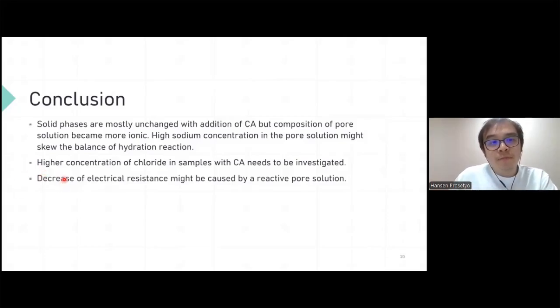We have a decrease of electrical resistance, as I said before. This might be caused by the reactive pore solution, but it's a cause for concern because it means that ions can travel more easily through the concrete. It means chloride can travel more easily inside the concrete. Okay.